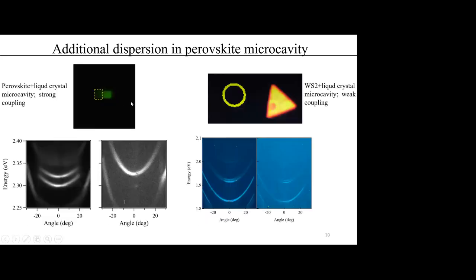In our experiments, we can also observe similar large curvature bands under 0 voltage. If we select the area near the perovskite microplate and measure the dispersion for this area, we can only observe the cavity modes, which do not couple with the excitons of the perovskites. The coexistence of these two kinds of dispersion cannot be observed in a weak coupling microcavity, which we plot in